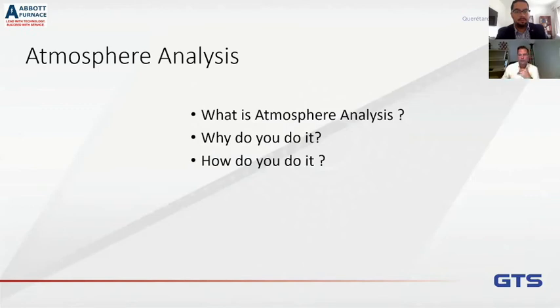The atmosphere analysis is a little bit different than the temperature profile. Here, what we're going to do is take a stainless steel or inox tube, and we're going to insert that from the front of the furnace and slowly move it through the furnace and gather a sample at each location as we travel through, so that we can look at what the atmosphere is in each location. In every section. But because it takes time for that atmosphere to get through that tube, we have to allow it to sit there for a while. So it's not going to travel through fast like the thermocouples do, or the Phoenix system. You insert and let it stabilize, and then you move it again and allow it to stabilize, and you gather that information.